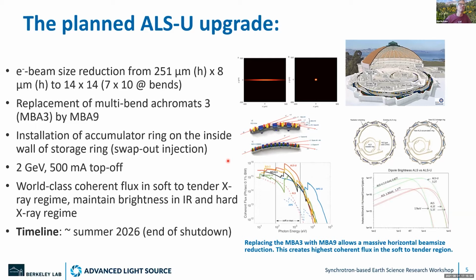The increase from MBA 3 to MBA 9 and the decrease in source size: the main effect of these upgrades is that the flux and brightness in the soft to tender X-ray energy range will go up to the highest of any synchrotron worldwide. In contrast, the higher energy range will go down a little bit.